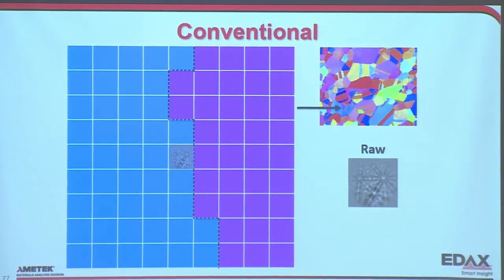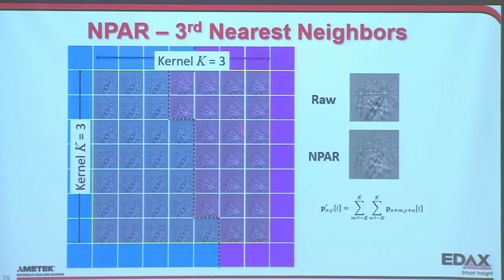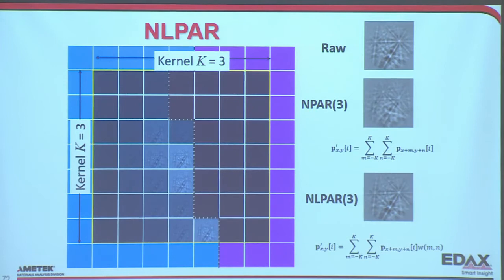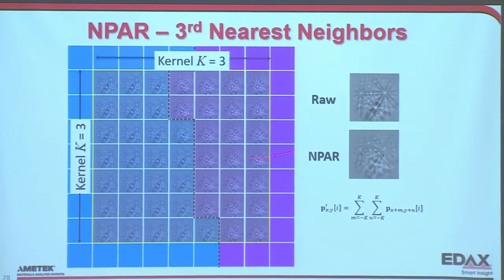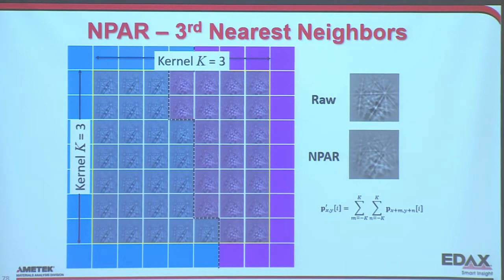So here's our raw pattern. We look at all the neighbors, and we come up with this difference scheme. And we're going to weight them now. So NPAR, if we did a big kernel like this, would give us this pattern, which is clearly a mix between this grain and this grain.